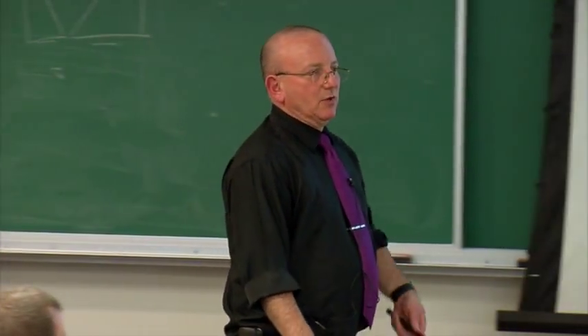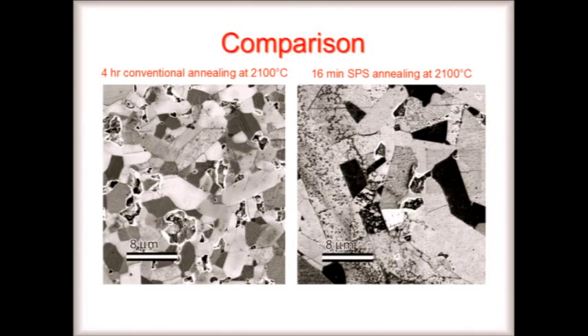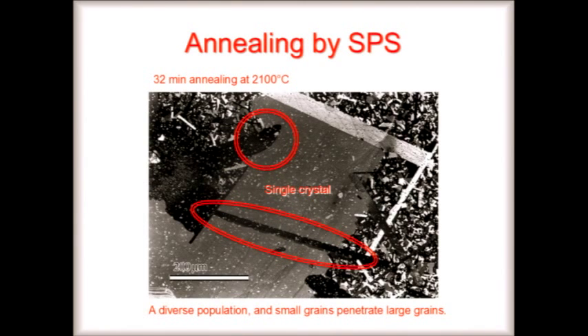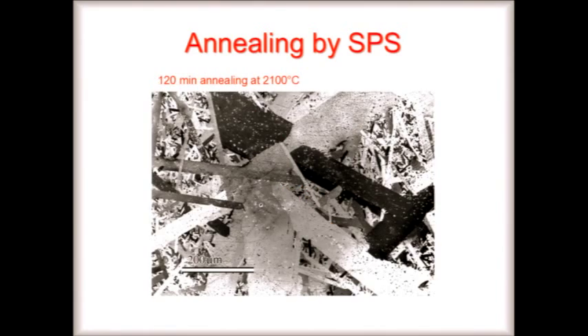My conclusion when I looked at this data the first time was, wow, this SPS sinters really fast. Isn't that lucky? Because otherwise they would never reach density with this stuff. Or at least, there's no way to control the grain size. This is 32 minutes, which nobody would do by SPS, but we got curious about the crystal size. You can even see impingement of small crystals growing into larger crystals. So something is really driving these grain boundaries to move.